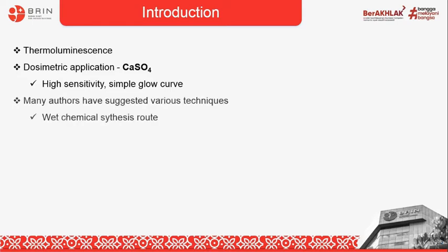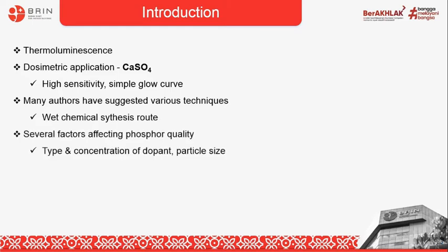Many authors have suggested various techniques for creating calcium sulfate phosphors, such as coprecipitation, acid recrystallization, mechanical alloying like ball milling, solid-state diffusion, etc. The wet chemical synthesis method was preferred as a low-cost and simple method, and it doesn't need any special instruments. Several factors affect the quality of the phosphor, such as the type and concentration of dopants in the host lattice, and also the particle size of the matrix.